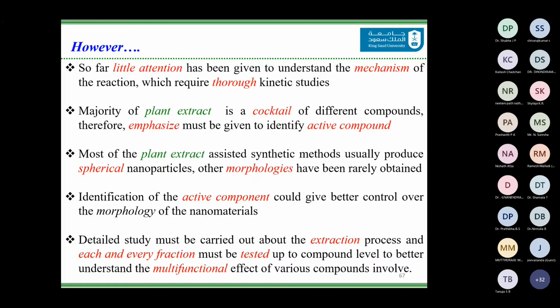So most of the studies that we have done, and there was a study where we tried to isolate the active component from a plant extract and synthesize nanoparticles using it. To our astonishment, we did not get the desired nanoparticles. The reason is these cocktails are working in synergy with other phytomolecules that reduce the metal salt or graphene oxide, as we have seen in our case.